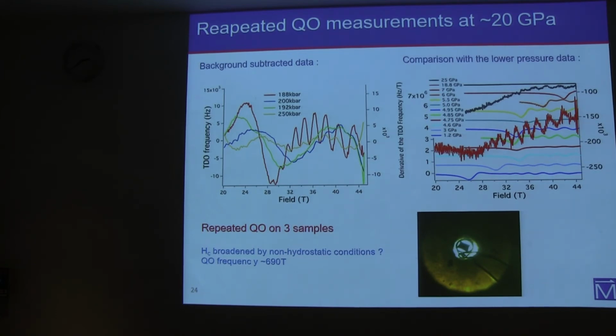So that was a technical comment here. But here I plot the background subtracted data for 4 different pressure cells at different pressures ranging from 188 kilobar up to 250 kilobar. And we see again the critical field transition here and the quantum oscillations. So not all of them show such strong quantum oscillations, but at least the 188 kilobar shows very strong quantum oscillations.